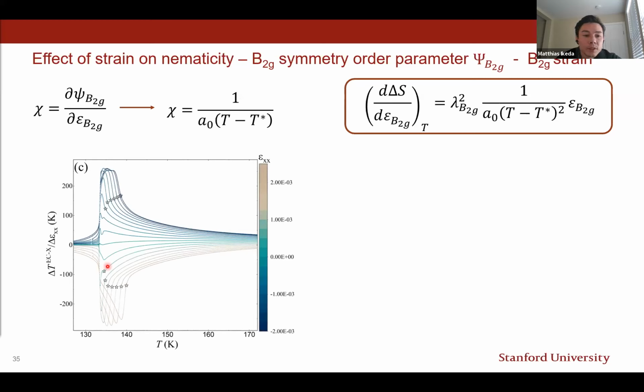We can see that we indeed measure an elastocaloric effect that is tunable in magnitude, but also the sign can be tuned by the amount of offset strain we apply. And we indeed see a diverging temperature dependence. Now it is possible to extract this coefficient by taking isotemperature cuts through our data and then just determining the slope as a response to strain.